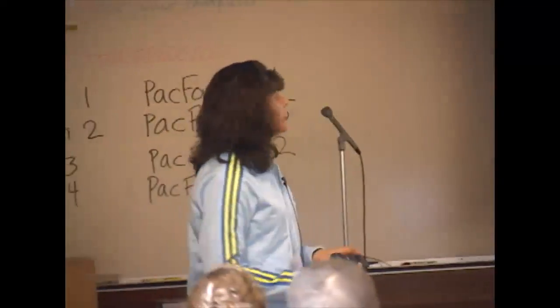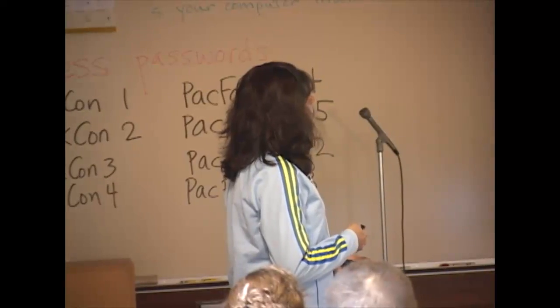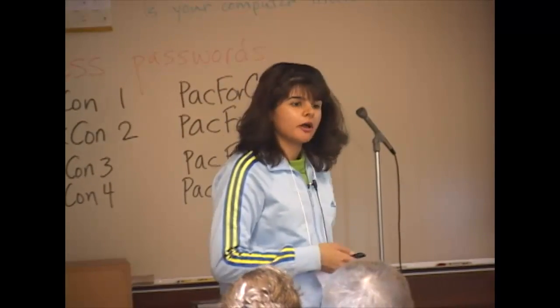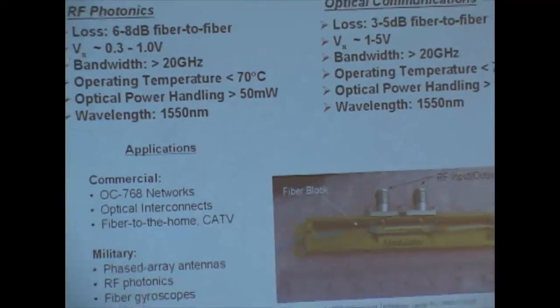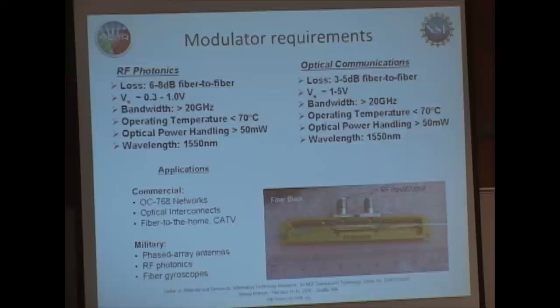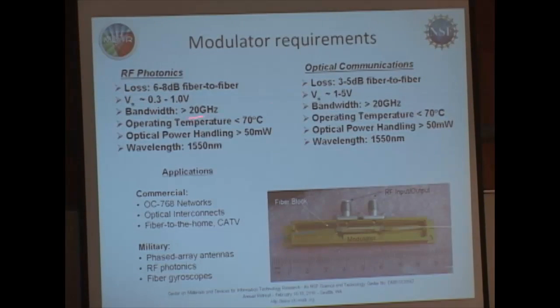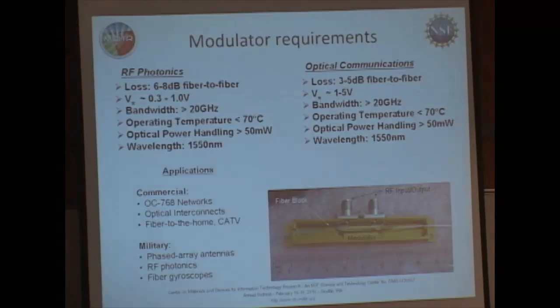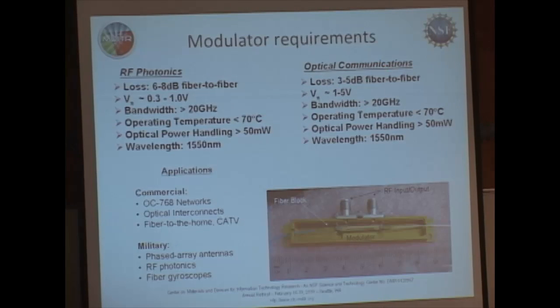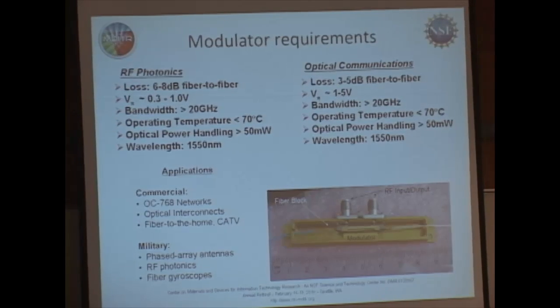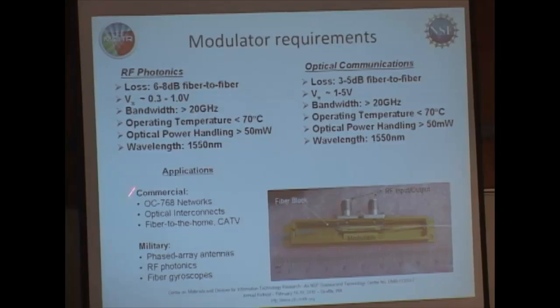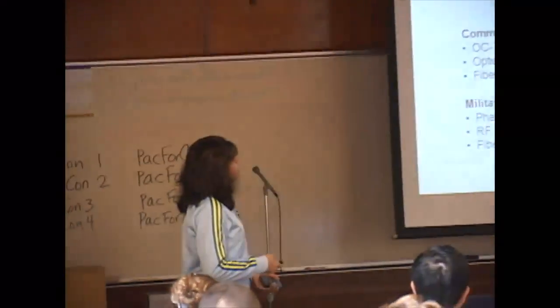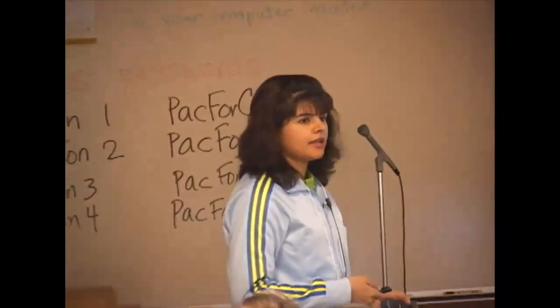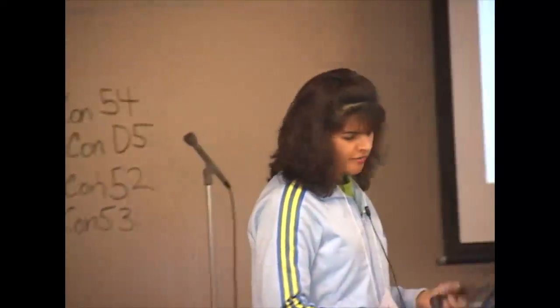So here are our typical modulator goals. We've got two different goals, one for RF photonics and one for optical communication. In general, we're working at 1550 nanometers and we want to operate below 70°C. And the main difference between the two are their loss and V-pi measurements, with the loss being much lower for optical communications and V-pi being lower for the RF photonics. And there's various applications, both commercial and military. And then here I show one of our packaged modulators that we designed in our new package design. And I'll talk about that later.